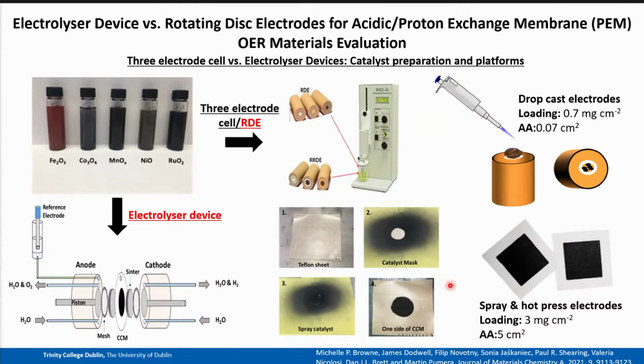And then you will get your Nafion membrane, and you will sandwich your two sheets of catalyst between the Nafion membrane and hot press. And then eventually what you get is a catalyst coated membrane, which you can see here. And the catalyst loadings and the active areas are significantly different compared to our rotating ring disc electrodes. So then after this, the catalyst coated membranes will be inserted into an electrolyzer device. So this is a schematic of the electrolyzer device that we use for this study.